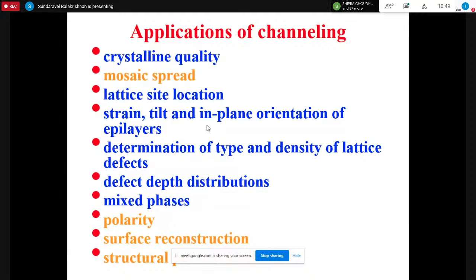So one can see whether there is any in-plane orientation of epilayers, and one can determine the type of defects, whether it is point defect, dislocation, or stacking fault, and what is the density of those lattice defects. And suppose you have point defects in the material, then what is the defect concentration as a function of depth, that we can see.